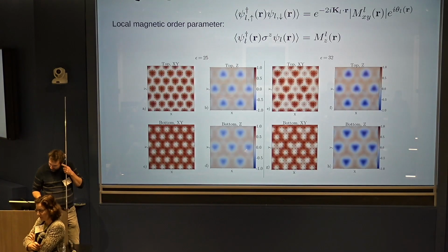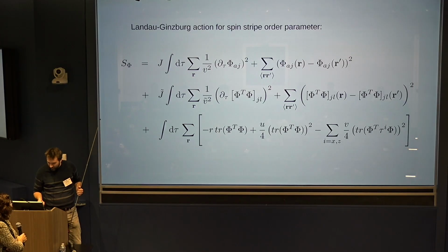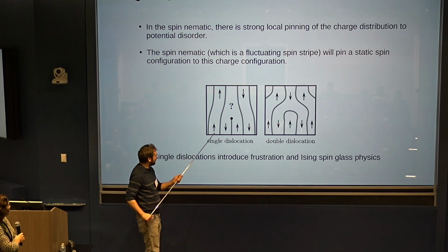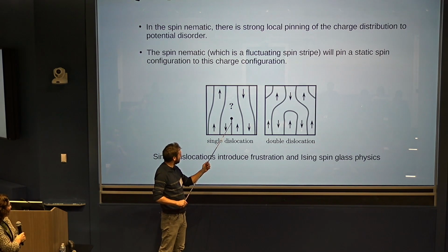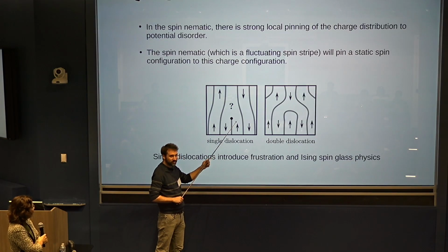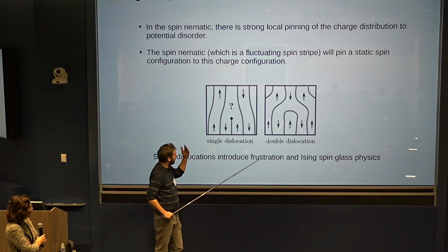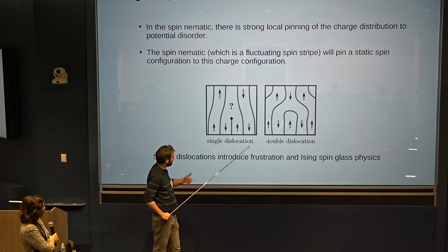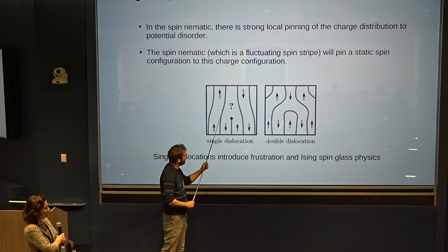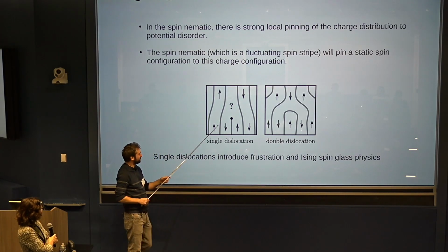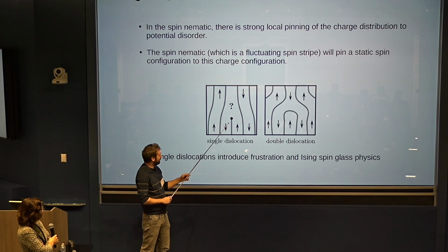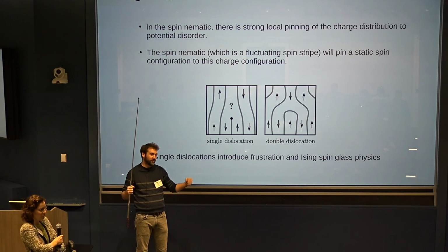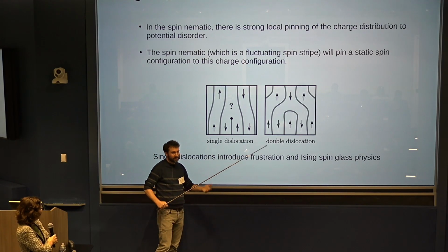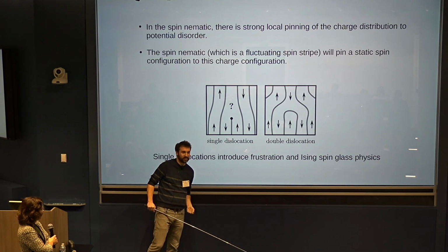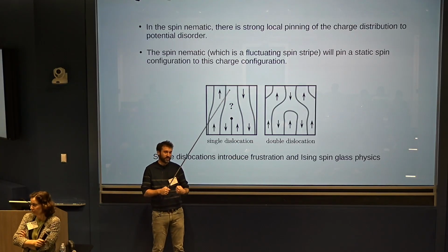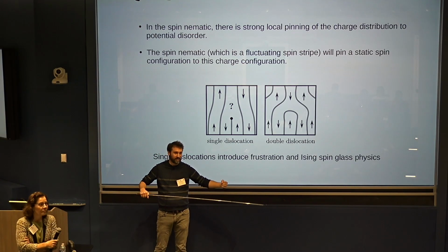You're absolutely right. Okay. Let me go back to my cartoon picture. Yes, one way to relieve the frustrations is to introduce a singularity. Also let the spins basically make a vortex and let them twist as you go around the singularity, right? Then you make basically the equivalent of a half vortex for the pair density wave state, which was introduced by people here in the audience. This is the equivalent of the half vortex, but for the spin stripe, right? Yes. But then, of course, you pay some logarithmic elastic energy associated with that. But indeed, if you have two dislocations close enough to each other, that could be rare regions where this happens. But as long as you have pairs of vortices and they don't proliferate, I think at long distances it's still Ising